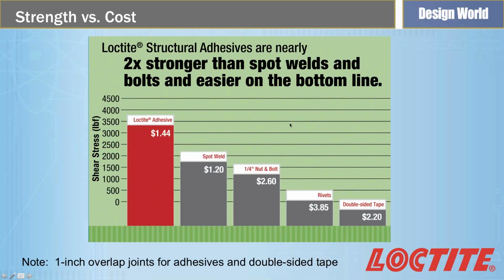So here's a graph I've alluded to, and this shows you the shear strength along the y-axis versus alternative fastening methods. For the adhesive on the far left and for the double-sided tape on the far right, I'm using a 1-inch overlapped joint to generate that shear stress. As you can see, Loctite adhesives can give you up to 3,500 pounds force of strength on a 1-inch by 1-inch overlap. The next one down, about half the strength, is a spot weld. The major differentiator there is that distribution of stress. If you're welding that whole 1-inch area, it's stronger than an adhesive. But when you do just a spot weld, it's not as strong. And you can see the strength curve go all the way down to double-sided tapes on the bottom there.